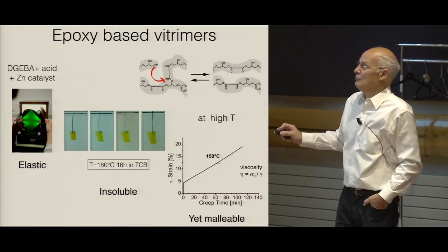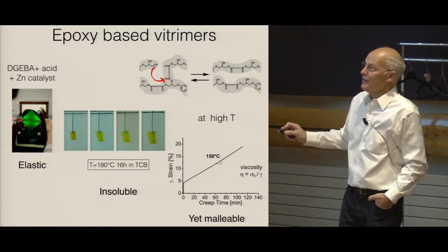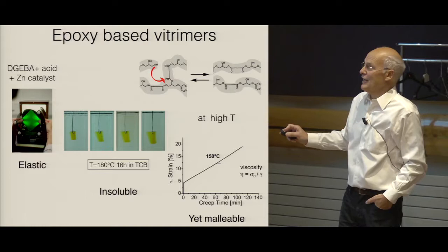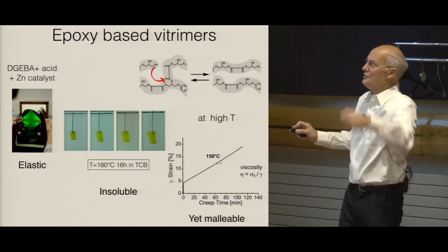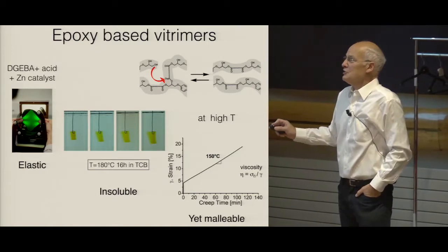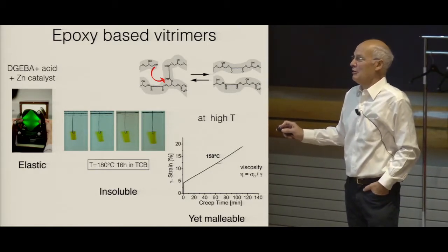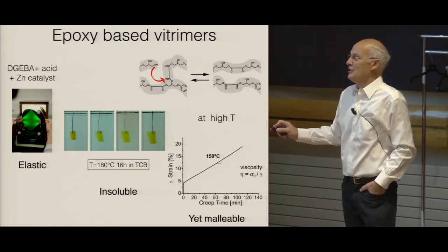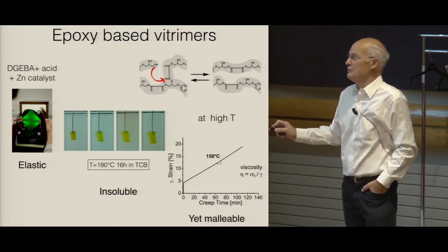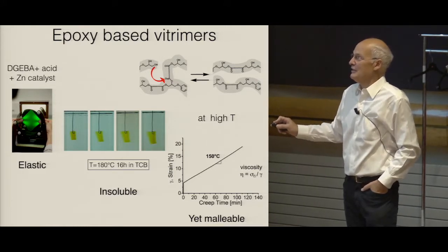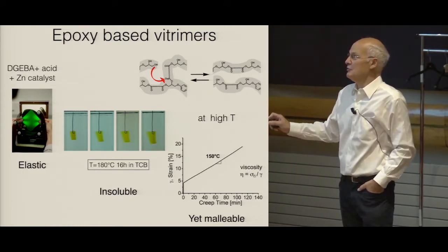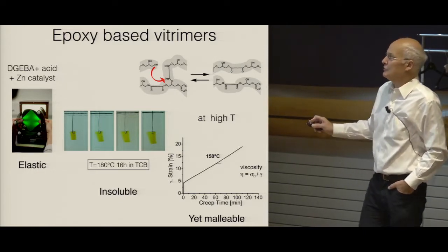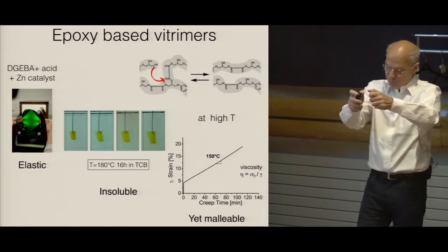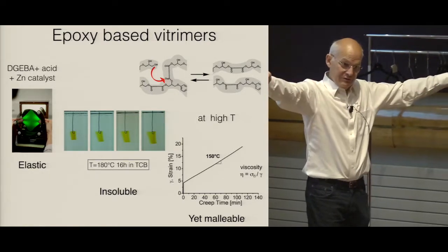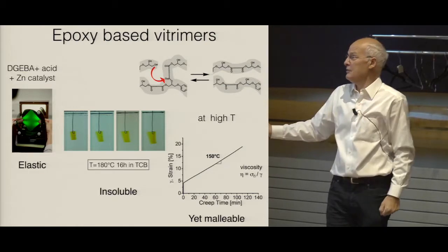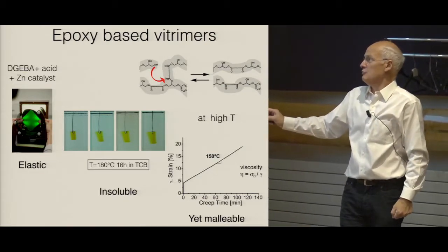And what you get is something which behaves like a rubber because it's a cross-linked polymer. It's elastic. It becomes birefringent if you pull at it. Yet if you put it in a good solvent, which is trichlorobenzene here, at 180 degrees for 16 hours in this experiment, you can put it for weeks, and it will swell, but it will not dissolve. And yet when you heat it to 150 degrees and you put a stress, then you see that it deforms, it flows, and loses its shape.